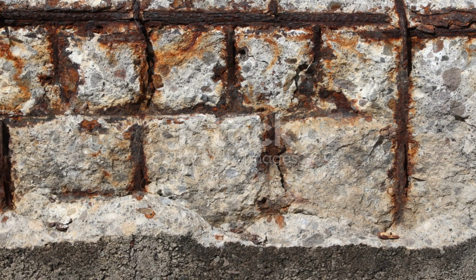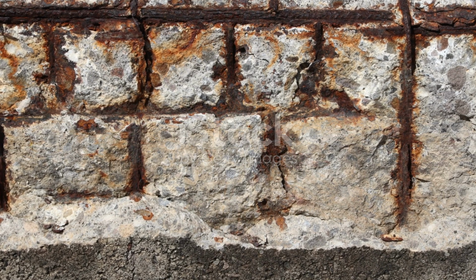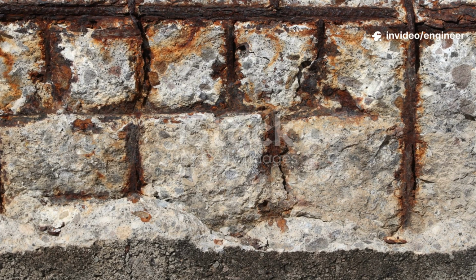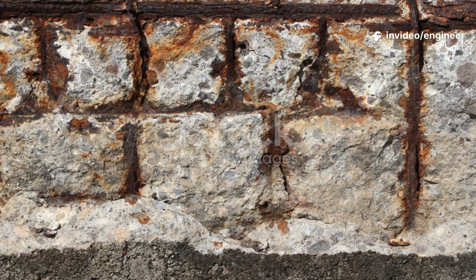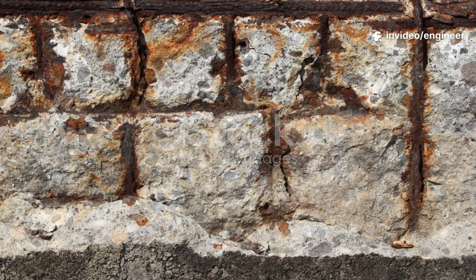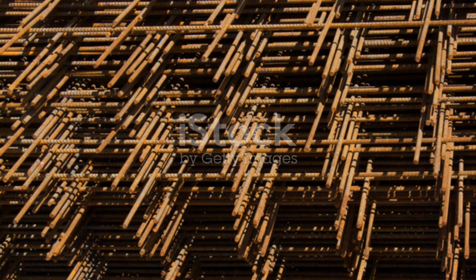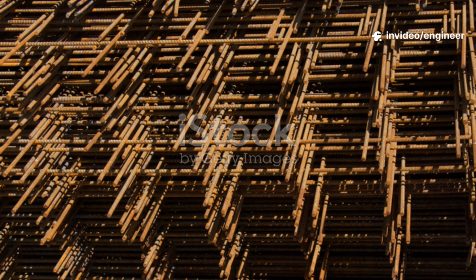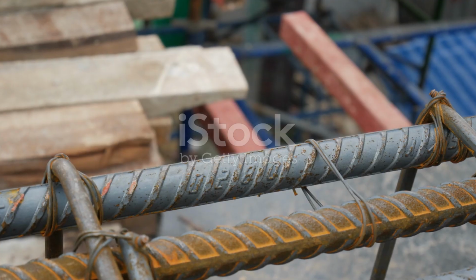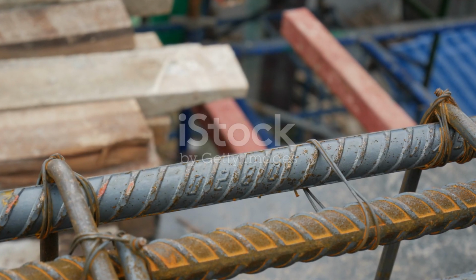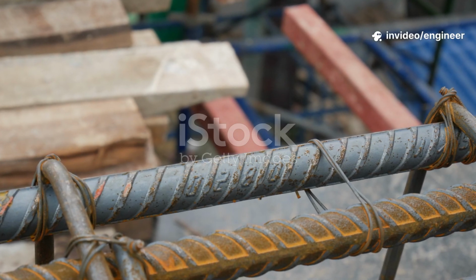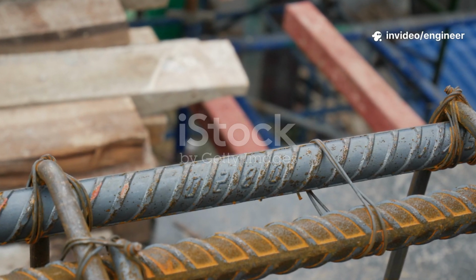Corrosion: rusted rebar expands, causing the surrounding concrete to crack and spall off. This is concrete cancer. Bars placed too deep inside the wall are less effective at controlling surface cracks. The fix: clear specifications and diligent on-site verification. Design drawings must show the rebar schedule: bar sizes, spacing, vertical reinforcement, spacing, horizontal reinforcement, required concrete cover. On site, workers must use bar chairs and spacers, plastic or concrete. These devices hold rebar away from the formwork.